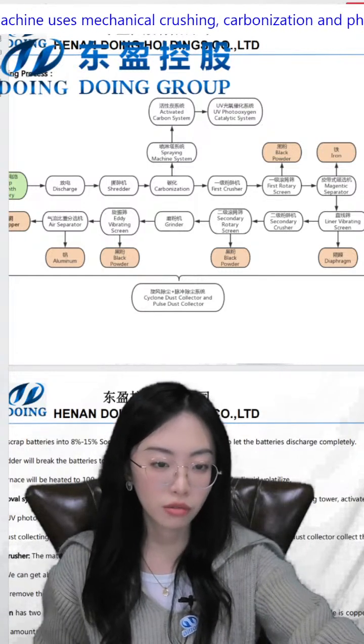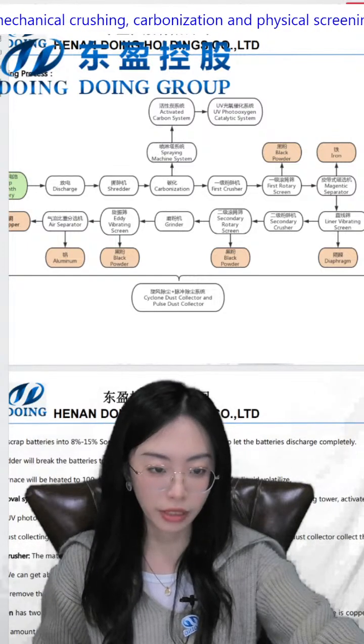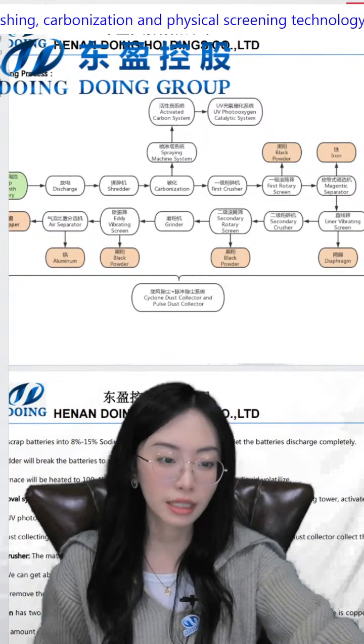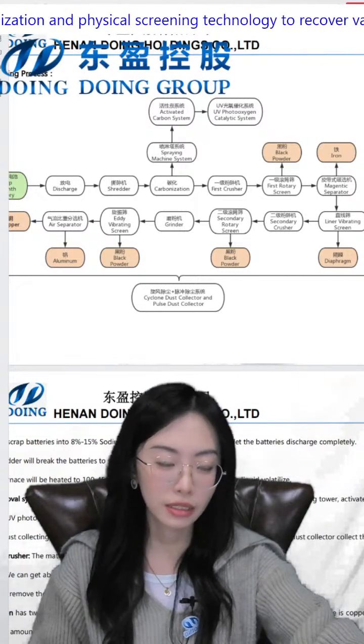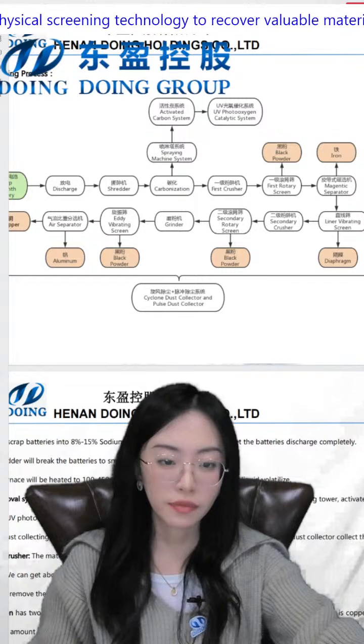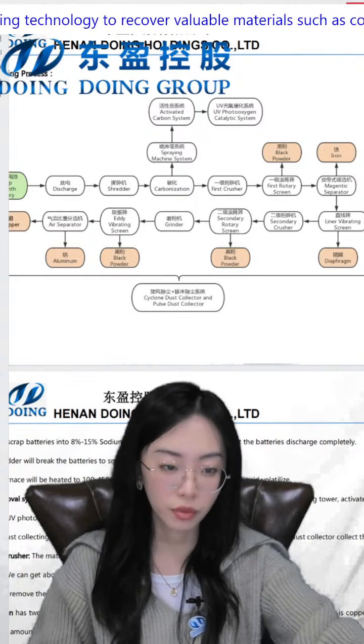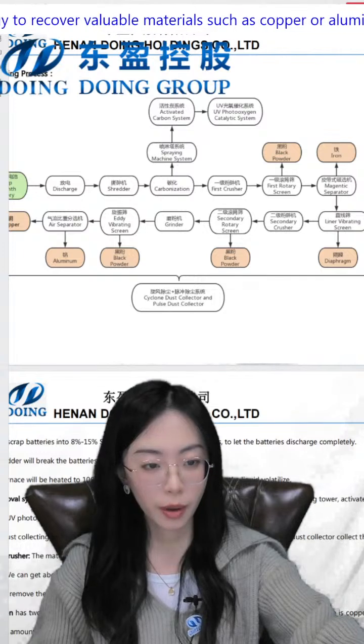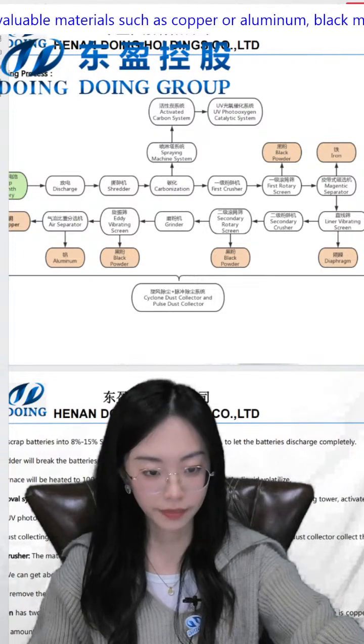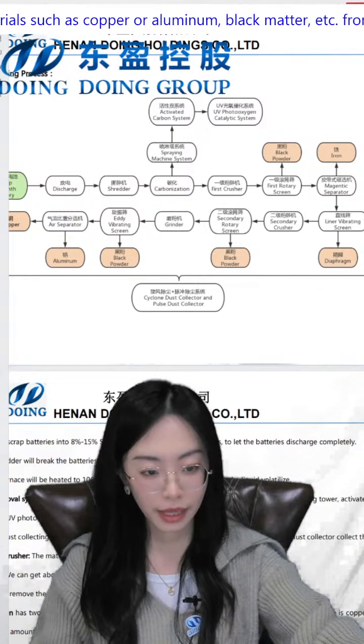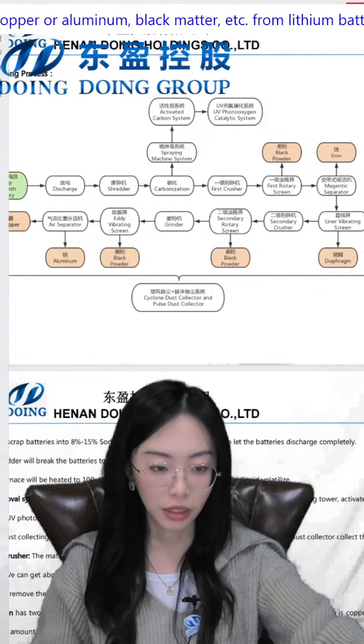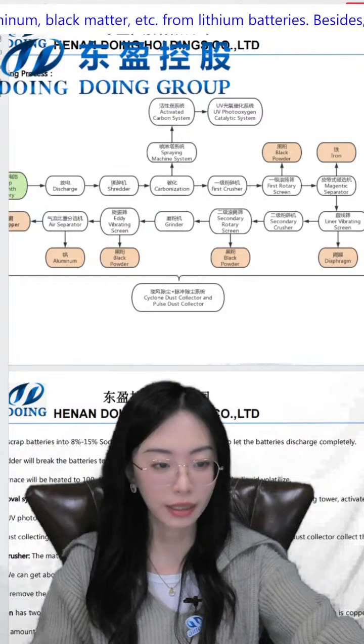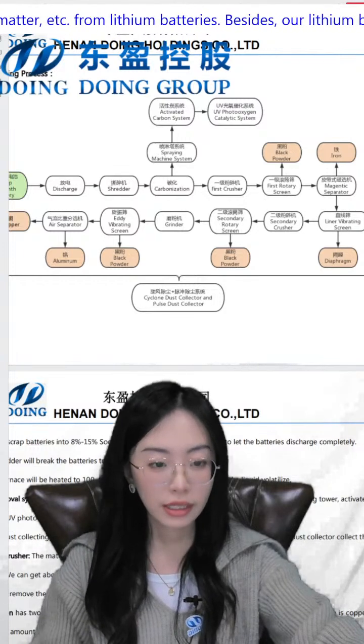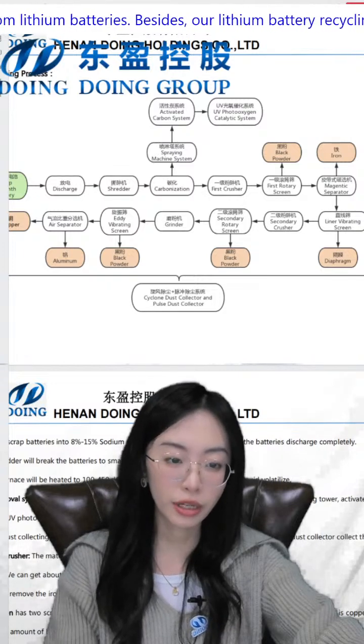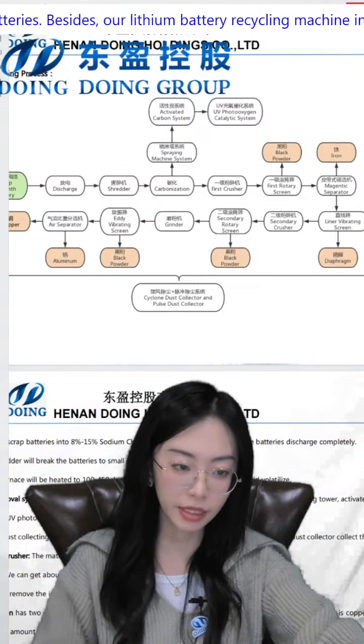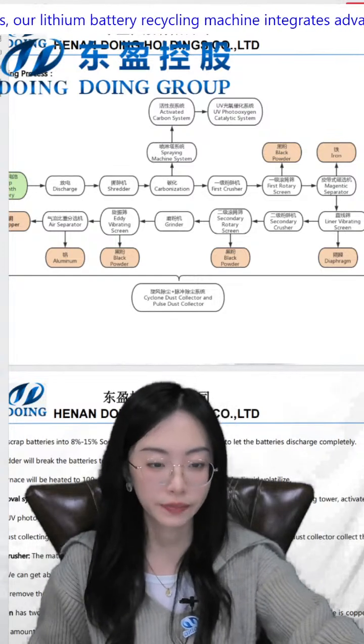The air separator, also called the air gravity separator, utilizes the combined action of the airflow and the vibration friction on the raw materials. So the large copper particles will settle to the bottom, and the smaller aluminium and plastic will suspend on the surface of the material layer by the action of the airflow. And in this step, the separation rate of the copper and aluminium is about 98%.